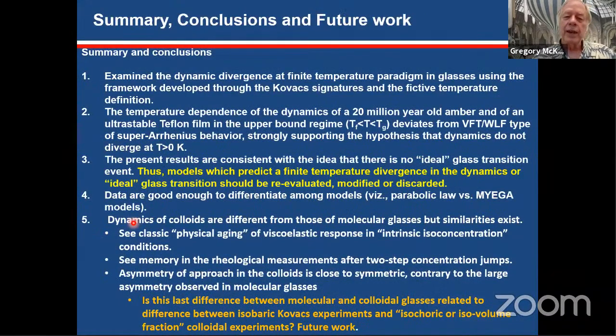So okay, I've tried to examine the divergence of finite temperature paradigm in glasses using a framework developed through the Kovacs signatures and the fictive temperature definition. The temperature dependence of the dynamics of a 20 million year old amber and of an ultra-stable Teflon film in the upper bound regime deviates from the Vogel-Fulcher WLF type of super-Arrhenius behavior, strongly supporting the hypothesis that dynamics do not diverge at T greater than 0 Kelvin, or at least, if they do diverge, it's at a temperature below the Vogel-Fulcher temperature. The present results are consistent with the idea that there is no ideal glass transition event. Thus, models which predict a finite temperature divergence in the dynamics or ideal glass transition should be reevaluated, modified, or, being extreme, discarded. Data are actually good enough to differentiate among models.